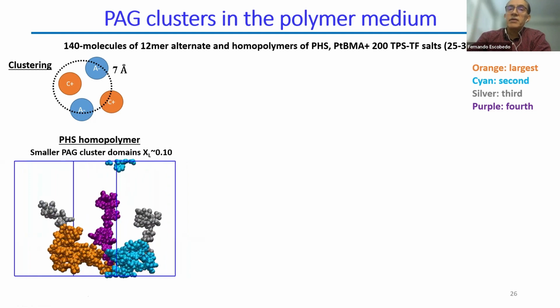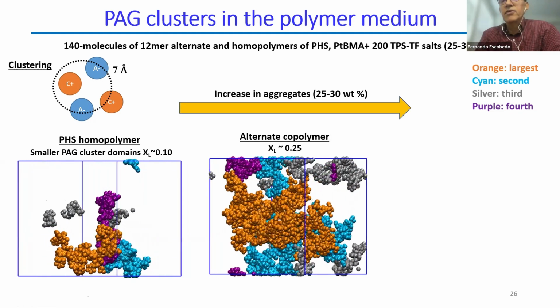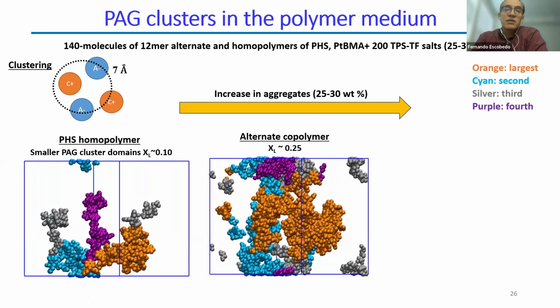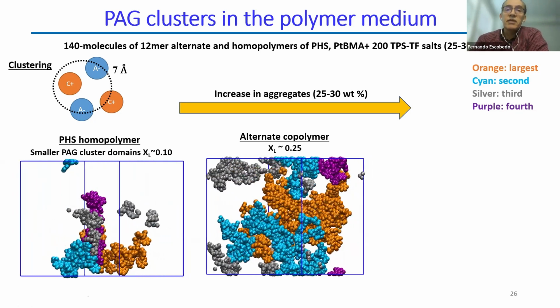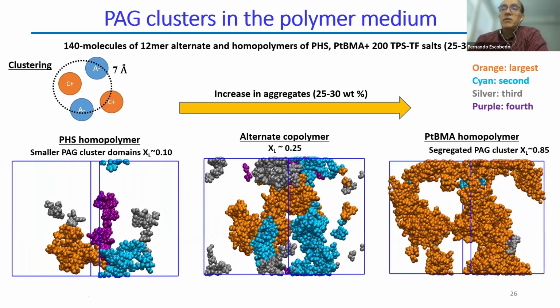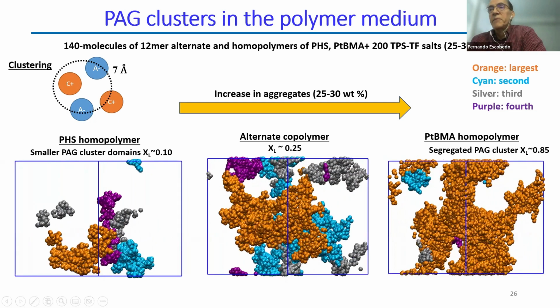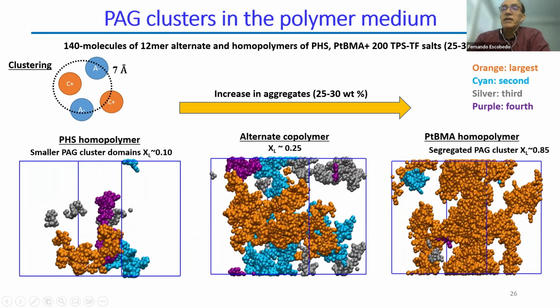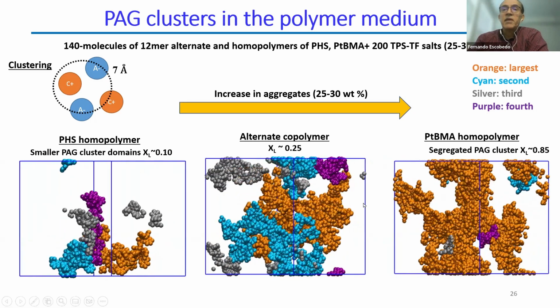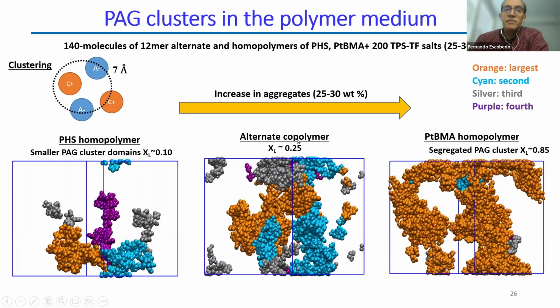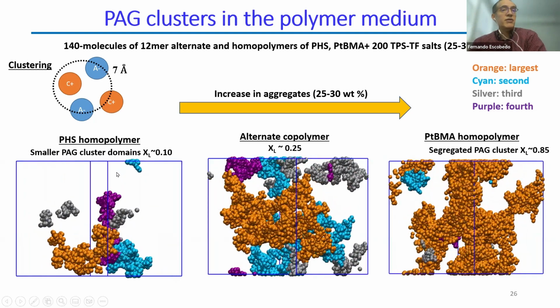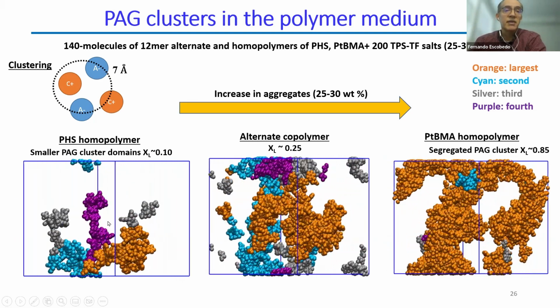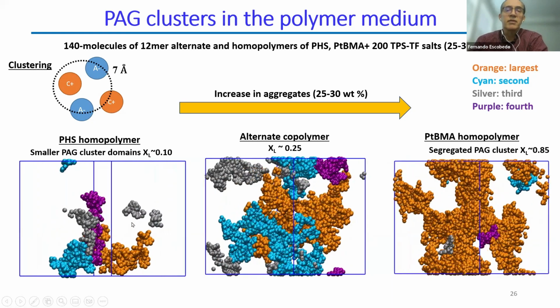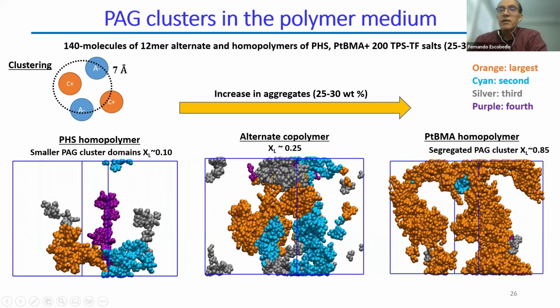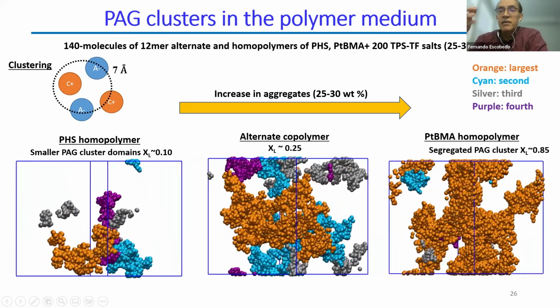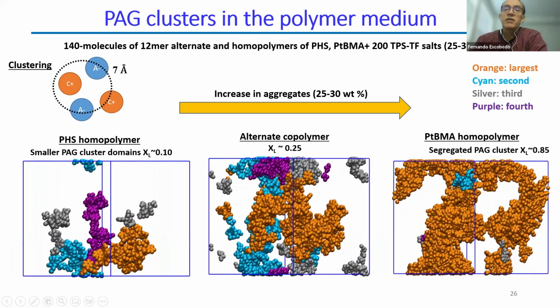And if you look at what happens in the alternate copolymer, you see that now the clusters are bigger. For example, in the largest cluster, now you have about 25% of all the salts. And when you look at the PTBMA homopolymer, it's much worse. Now you see that you have 85% of all the salts in the largest cluster. So in this context, I would say that the PHS scenario, if you could just use PHS as your photoresist, would be ideal, because I think these clusters are small enough not to bother you. Even the alternate copolymer would be potentially okay. These feature sizes are perhaps small enough to not bother you too much.